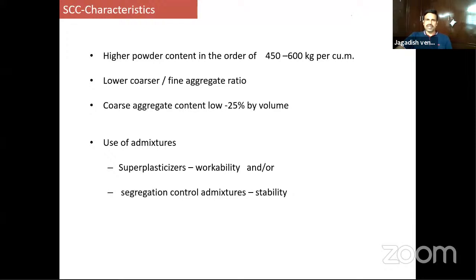How are the properties different from normal concrete? In normal concrete, the powder content is between 300 to 450 kg per cubic meter. But in case of SCC, the powder content varies between 450 kg per cubic meter to 600 kg per cubic meter. So the minimum itself is 450, up to 600 kg is the powder content. In normal concrete, if you take a normal mix of M20 grade, the fine aggregate varies between 700 to 800 kg per cubic meter, and coarse aggregate varies between 1200 to 1400 kg per cubic meter. But in case of SCC, there is a lower coarse to fine aggregate ratio. That means both coarse and fine aggregate are in equal quantities, or sometimes the coarse aggregate is in lower quantity when compared with the fine aggregate.